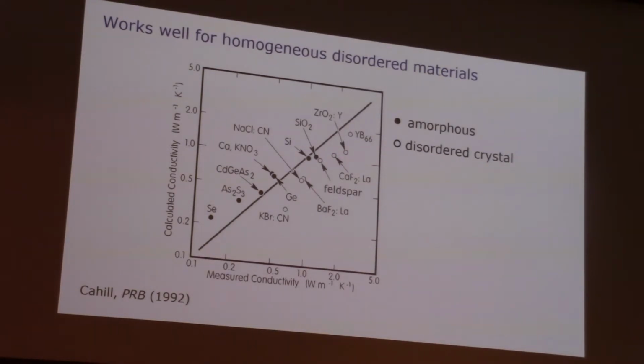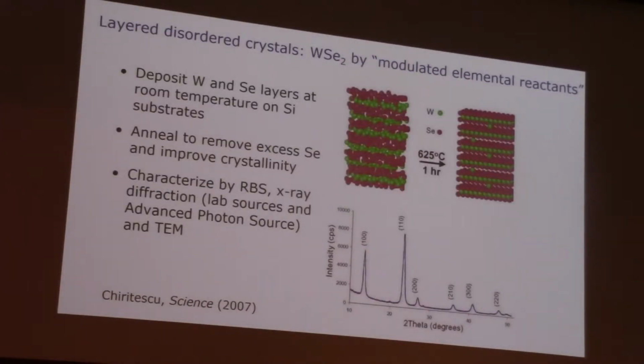And then there were many attempts since then to try to do better, so find something with lower. And I won't go through all the details, I'll just skip ahead to the first one that was successful in a bigger way at producing a thermal conductivity much smaller than this amorphous limit. And what we observed that in is a tungsten diselenide material, which was created by the modulated elemental reactant method. And what that means is, think of it as a materials chemist version of MBE. So you deposit atoms on a cold substrate in the right order, in the right ratios, then anneal it to form the material that you want to form. So it's kind of a low temperature deposition followed by annealing.